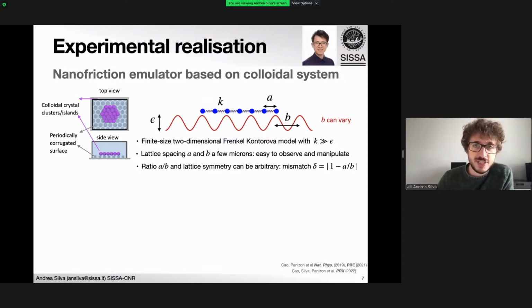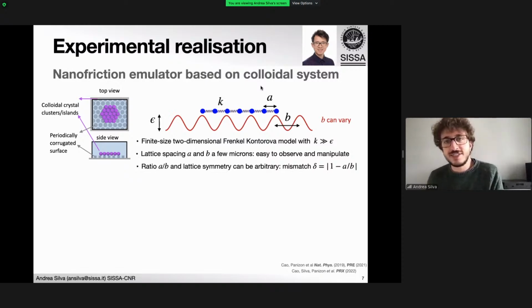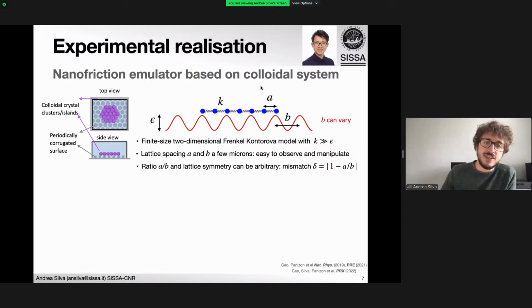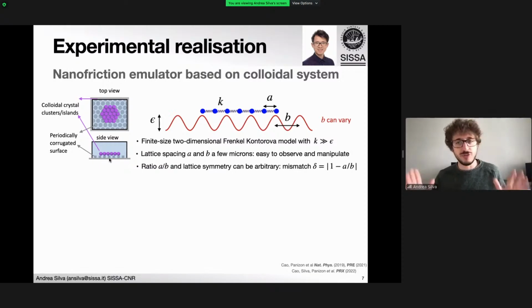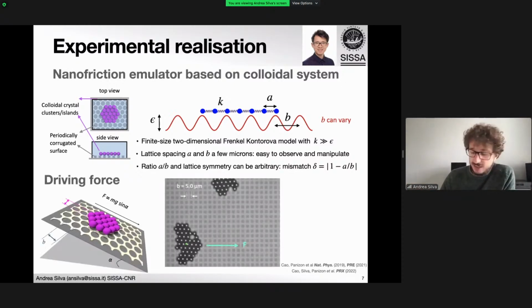Not quite a nanoscale interface, but what we call a nanofriction emulator, which is a colloidal system that emulates a real atomic interface, where we have these colloidal clusters over a patterned surface where we can tune the symmetry and strength of the substrate potential, mimicking two crystals basically meeting and pressed against each other. We can drive it like in a friction experiment using gravity, and we can see that this cluster moves along the patterned surface along a specific direction, going with some directional locking.